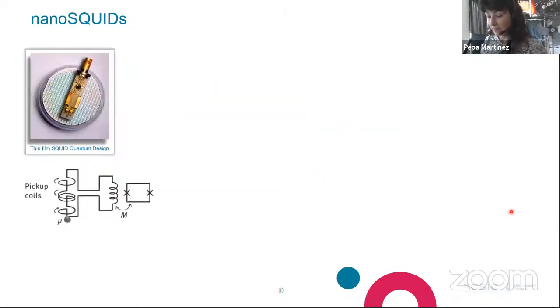So most of you have for sure worked with squids when characterizing magnetic materials, especially with commercial magnetometers. Here you can see an image of a typical squid from the company Quantum Design that many of you will for sure know. These devices usually work in the following way. You have one pickup coil circuit that couples the signal of your magnetic sample and is then later inductively coupled to your squid. This is made in this way so that the squid can be well shielded from the externally applied magnetic field that you need to excite your sample, because squids are superconducting and they don't like to be operated in magnetic fields.